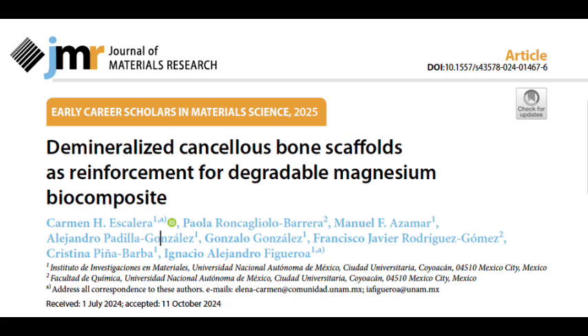So the carbon coating on one of the DBMs actually prevented the magnesium from fully reacting with the DBM. Interesting. So what happened was it created a thinner MgO layer. How thin are we talking? Like 10 to 20 micrometers. But the composite made with the non-coated DBM had a much thicker MgO layer. Oh, wow. So like twice as thick. Almost, closer to 40 micrometers. And that made a difference. Huge difference. It affected the strength of the composite in a big way.